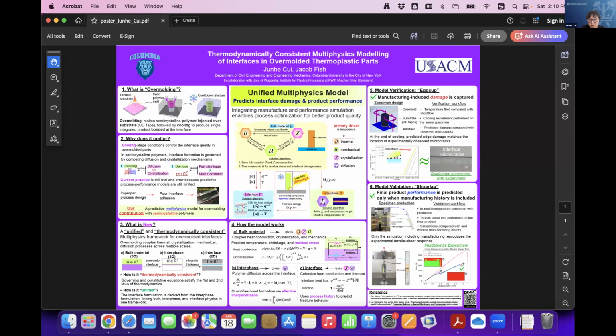The main message is that the manufacturing history shapes the interface states, and the interface states control the final product's performance. And finally, to show the model is accurate, we first verify it with this ECA specimen. Since the temperature is the primary driver, we first verify our predicted temperature field with the mold flow solution. And then we compare our predicted interface damage with the experimentally observed interface macrocracks. And our predicted concentrated interface damage agrees with the experiment. Now we can see our model is able to capture the manufacturing-induced damage given the processing conditions.